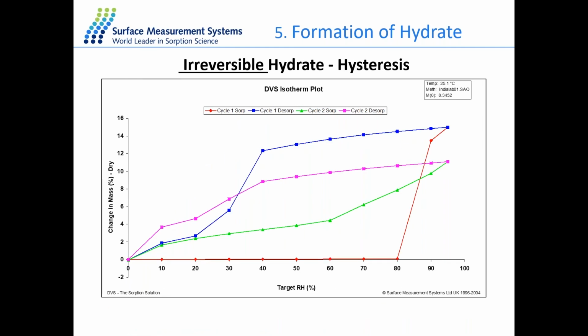We also have an example here about irreversible hydrate formation. We also do 2 cycles of moisture sorption and desorption on the sample. The red line is for the sorption in the first cycle, the blue line is for the desorption of the first cycle, and the pink and green lines are for the second cycle. This time, during the second cycle, it's not at the same level as the first cycle anymore. It's not overlapping with the first cycle.